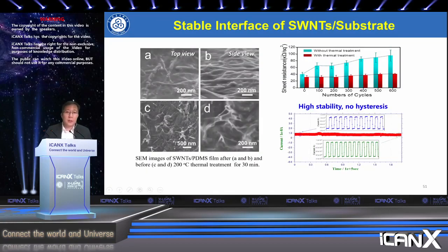And there are many details in this process you have to handle to make this device very stable. For example, the interface is very important. From here, you can see that the small bundles of single-walled carbon nanotubes were tightly adhered to the patterns of the PDMS substrate after the thermal treatment. And because of the strong van der Waals force between the single-walled carbon nanotubes and the PDMS substrate after the thermal treatment, it is energy favorable for the single-walled carbon nanotubes to adhere tightly to the substrate instead of uplifting from the substrate. And this figure shows the SEM of the single carbon nanotube PDMS film interface without the surface treatment. There are protrusive structures of the single-walled carbon nanotubes, which are quite different from the tightly attached single-walled carbon nanotubes after thermal treatment.